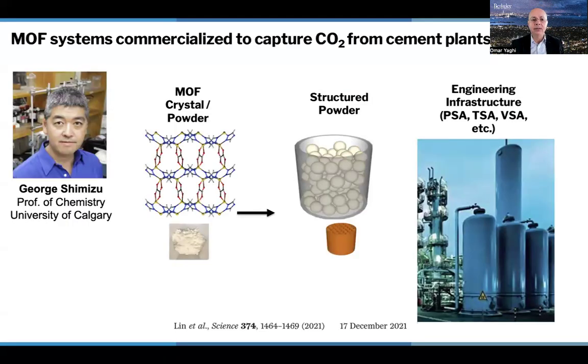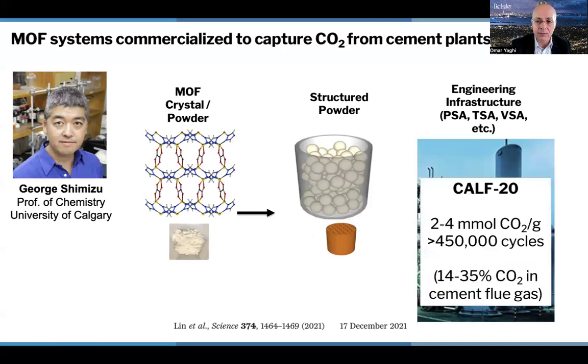So here is a MOF that was made based on our chemistry at the University of Calgary by Professor George Shimizu's group. This MOF is called CALF-20. It's a zinc carboxylate imidazolate MOF, and this was published back in 2021. It's being scaled up and is being tested in pilot plants already, several pilot plants. So this MOF is very special because it takes up a lot of CO2, so 2 to 4 millimole of CO2 per gram, and it's been cycling over